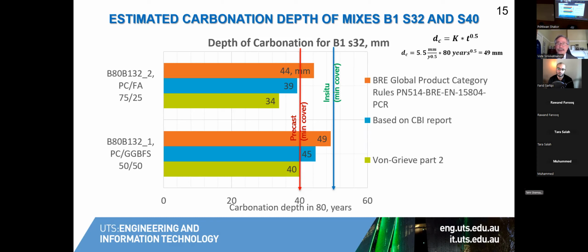And for a structure with a design life of 100 years, under carbonation-induced corrosion, it is very safe to design the structures with an initiation period of around 80 years and a propagation period of 20 years, making up 80 plus 20, making up the 100-year design life. Okay. In this case, we are looking at different concrete and different carbonation depth. Of course, to get carbonation-induced corrosion resistance, we need the quality of the concrete as well as the cover depth, which will control the design life of the structures. I'll just show you this example without going too much.